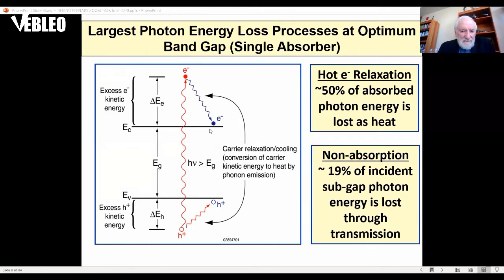So that's why the efficiency calculated by Shockley-Queisser, which is 32% as the maximum thermodynamic efficiency, assumes that all of these hot electrons cool to the edges of their respective bands. So the electron cools to the conduction band, the hole cools to the valence band, and that loses about 50% of the absorbed photon energy and converts the excess energy into heat.